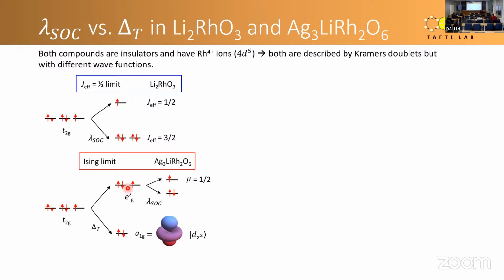Now that EG prime manifold then under spin orbit coupling also splits into 2 levels. And when you put 5 electrons in these 3 levels, you end up with 1 electron in the top level. That electron now is in the top orbital that came from EG prime. Therefore, this electron, even though it's a spin half, so you again get a spin half, is a purely spin half state. It doesn't have an orbital angular momentum component. L is 0. You have S equal 1/2. Unlike the top case in lithium rhodate, where you actually have L plus S or J being 1/2. And these two states are quite different.